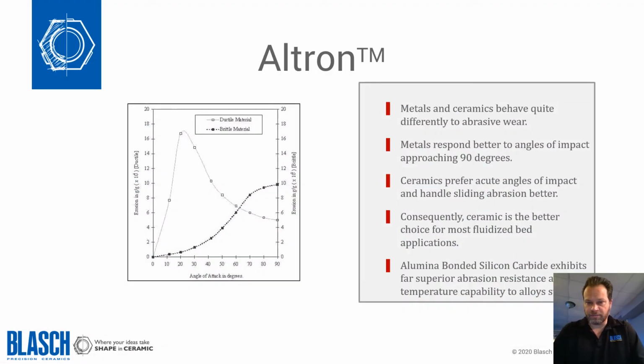Altron was eventually developed, and we saw some exceptional abrasion resistance with this material. Through a test called ASTM C704, it's a direct 90-degree impingement onto a roughly 4.5 inch square plate. We were achieving numbers approaching 1.5. If you're not familiar with the test, anything that is approaching zero is excellent. It's basically a measure of how much material is removed from the surface. So something in the 1.5 range, a little under 2, was an exceptionally abrasive material that worked well for the